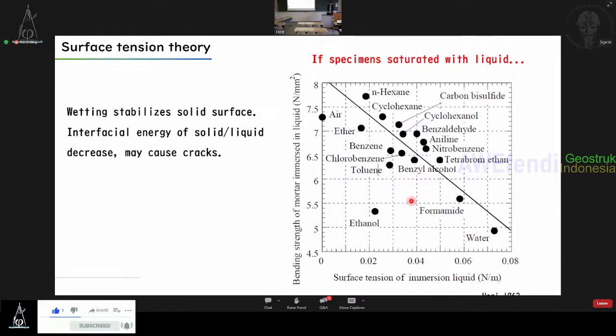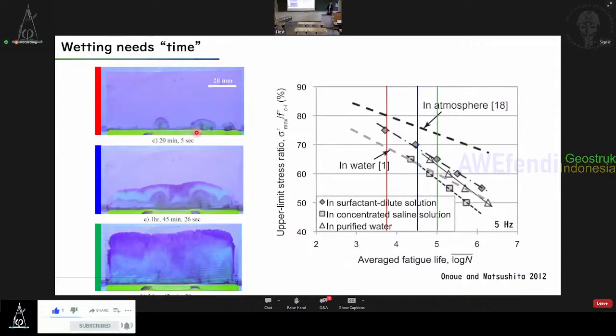When we think about underwater fatigue, there are some literature. Many previous studies show the surface tension theory: wetting fills such small pores and stabilizes the solid surface. Solid means the cementitious hydrate surface, and then the interfacial energy between solid and liquid will decrease, and that may cause cracks. But this hypothesis holds only when the specimen is fully saturated with water. But again, cement has many pores, and it takes time to be saturated.